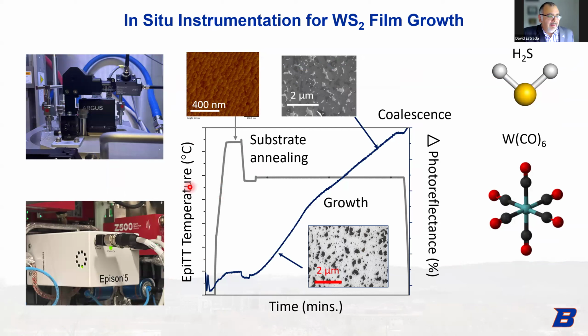You see here the temperature monitoring and then the photoreflectance change. We do a substrate anneal based on Professor Redwing's work with H2S, so we can anneal at high temperature and reconstruct the sapphire surface. This is just a hydrogen anneal. I'll show you the H2S anneal shortly. Then we can drop the temperature, do our nucleation, and keep the temperature constant for our growth while the photoreflectance increases. At some photoreflectance change, which you calibrate for your system, you get the full monolayer coalescence, right?